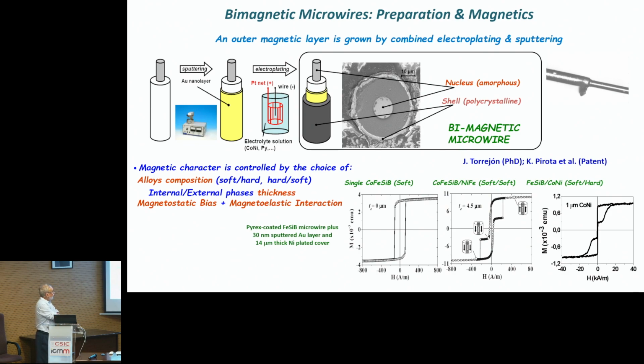Other applications were developed with a new family of magnetic wires, so-called bimagnetic wires. We start with a glass-coated microwire. We sputtered a tiny nano layer of gold, and then by electroplating, we grow an external magnetic shell. This is a cross-section of this bimagnetic wire. This is the internal core, the pyrex in the middle, and the magnetic layer on the outside. So we have a magnetic wire with two magnetic materials inside.